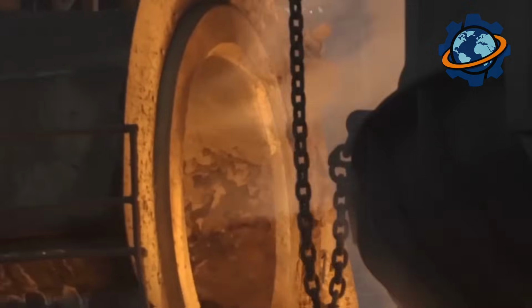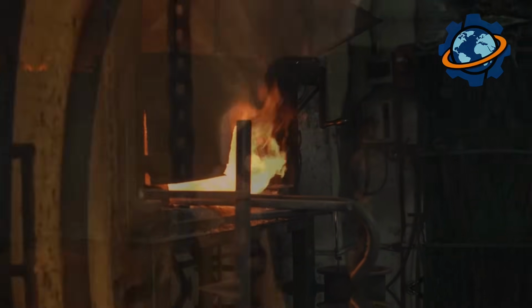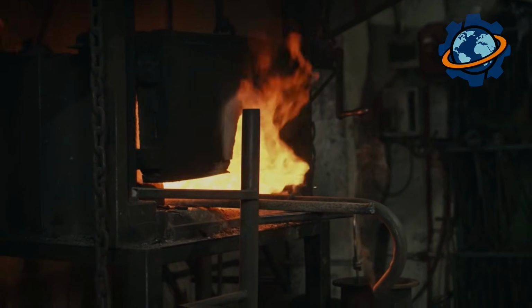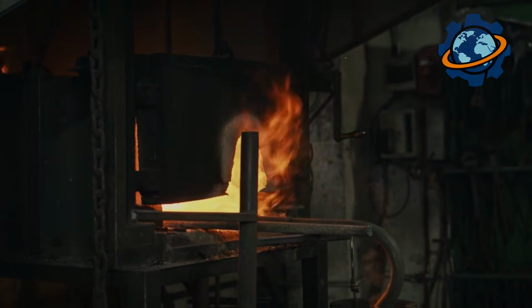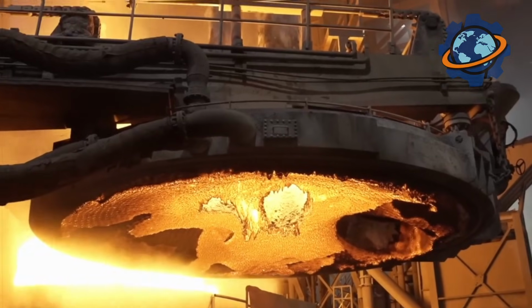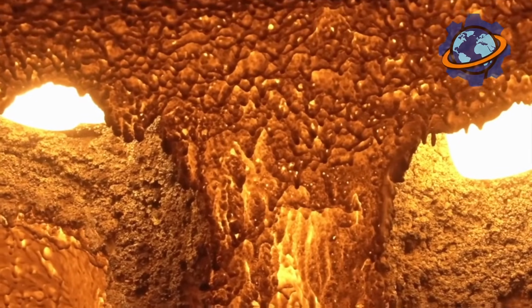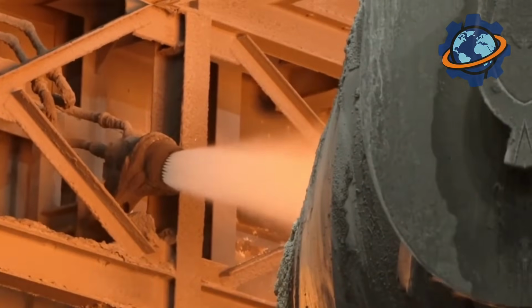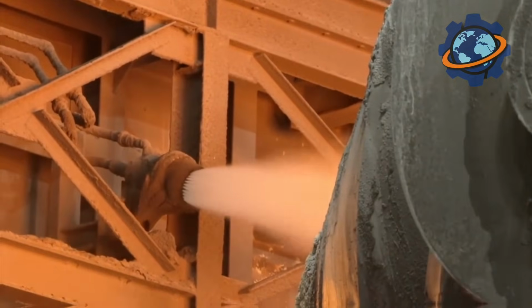Sparks and molten drops fly everywhere. The blowing process takes 20 minutes. In this time, 350 tons of pig iron become steel. Carbon burns down to 1% or less. The converter tilts, steel pours into a ladle. The molten metal glows blindingly white at 2,900 degrees Fahrenheit.